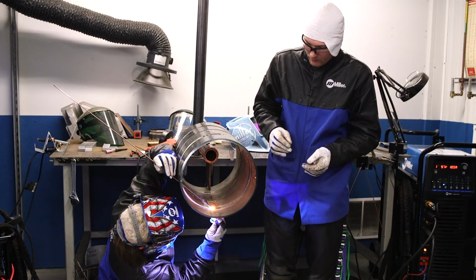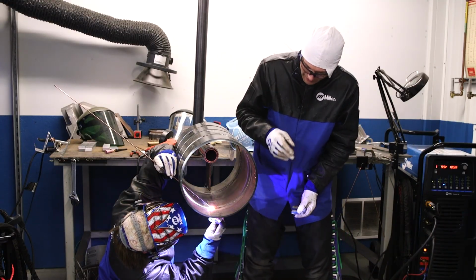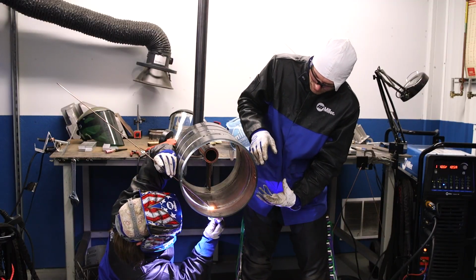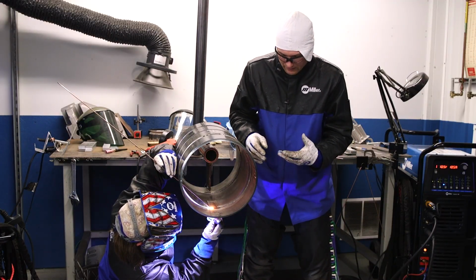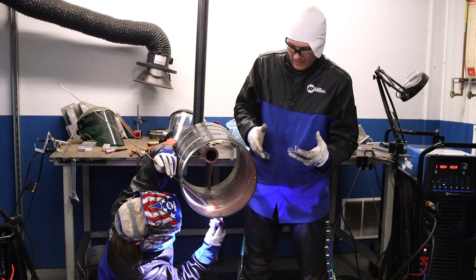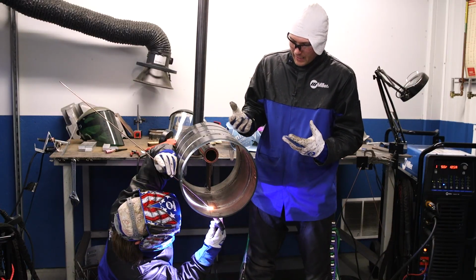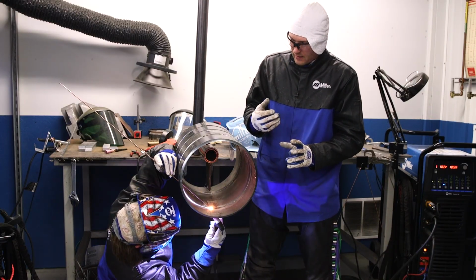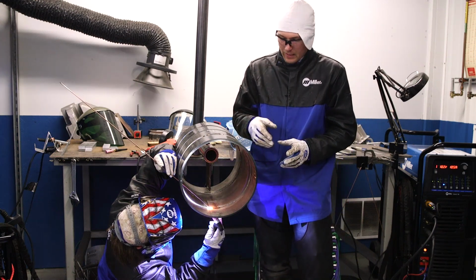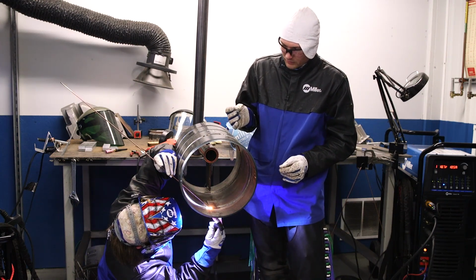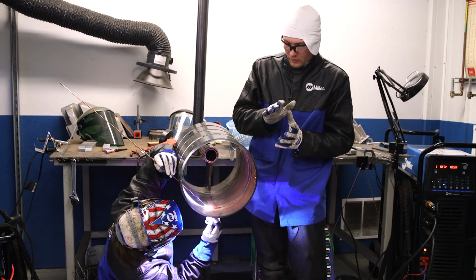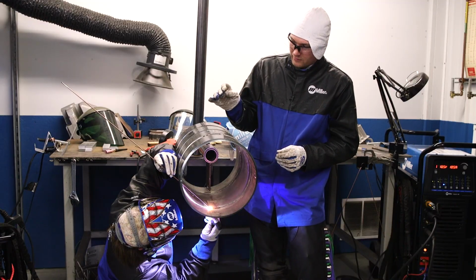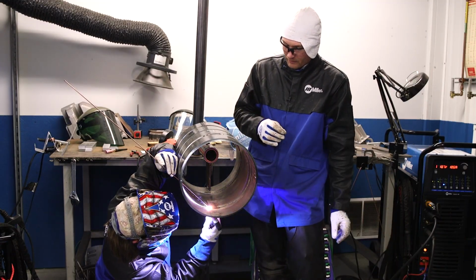But also at the same time, when you're using this technique, you can have your line of sight line up so where you're pulling the weld puddle up towards you, you can see the external leading edge of the puddle and the internal leading edge of the puddle. While the external leading edge of the puddle turns to a liquid, the internal leading edge a split second later will turn into a liquid. It'll go from a solid to a liquid, and that's when you can take the tip of the filler metal and add it to that weld puddle.